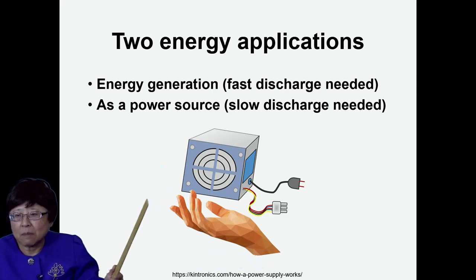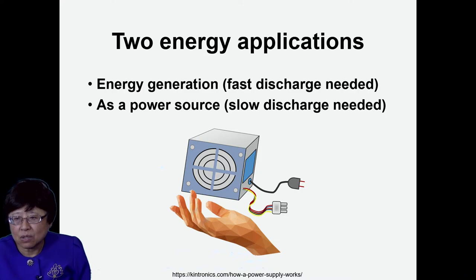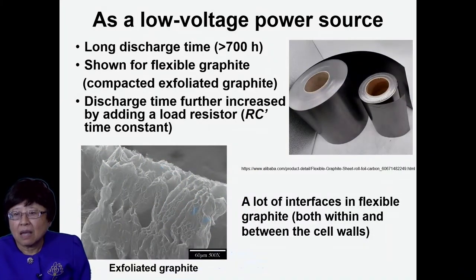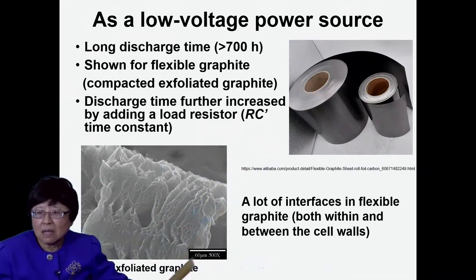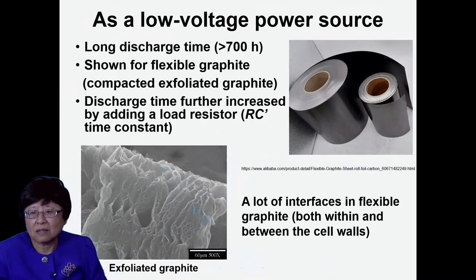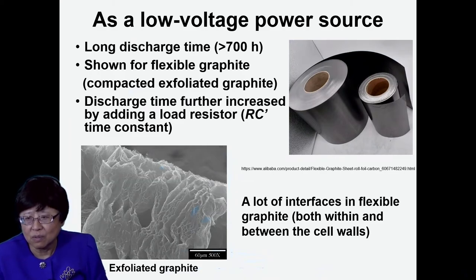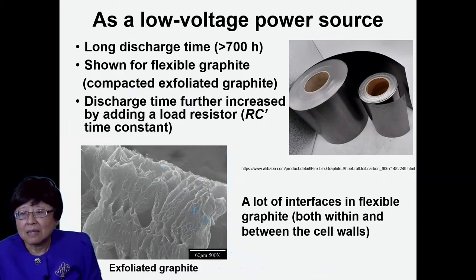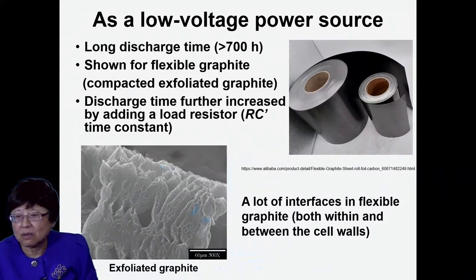And now I'd like to talk about the second application, the power source application. It's a low voltage power source. And we found that exfoliated graphite based flexible graphite is particularly good for that, with long discharge time exceeding 700 hours. And the discharge time can be further increased by adding a load resistor so that the RC time constant is increased.